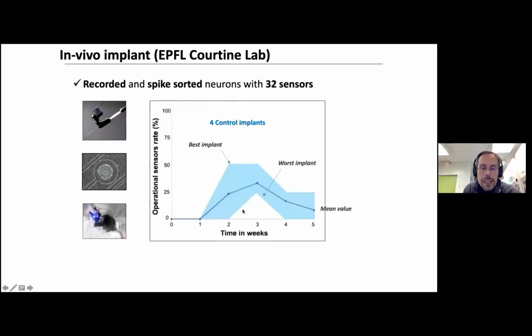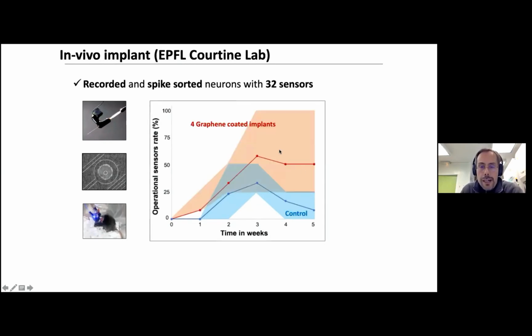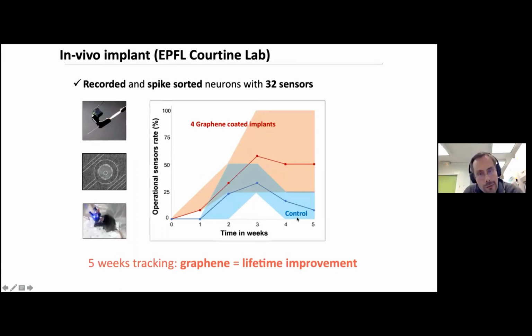And if you look here, for example, in time in weeks, at the measurement of this probe taken in situ, you have a much longer signal. You keep it much longer, up to 5 weeks, compared to the commercial implants. And these graphene-coated implants could have a very long-term application here.